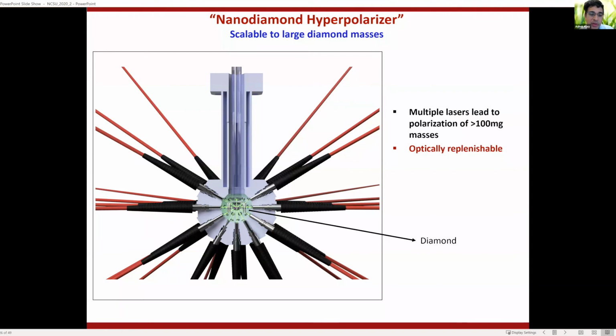Yeah, so this is a new iteration, and it's a very good question. Although per particle, the thing is quite efficient, first of all, the effective T1 of these spins is tens of seconds, 20, 30 seconds. That's nice. That gives you already some space. But here we're actually dumping 30 watts or so into the sample.